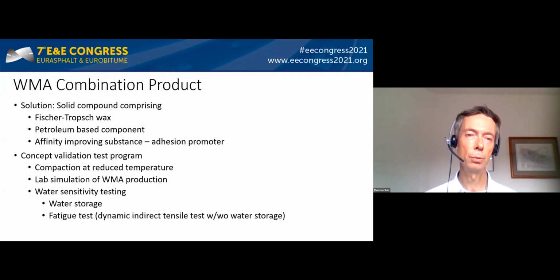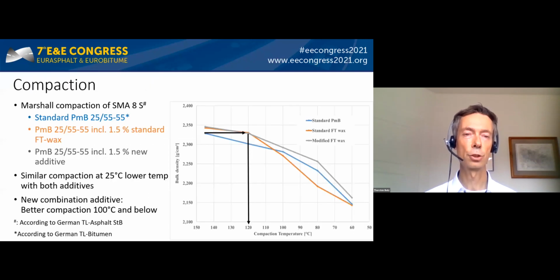Our concept was validated with the following test program: compaction at different reduced temperatures, laboratory simulation of warm mix asphalt production, and finally water sensitivity testing, applying dynamic indirect tensile test with and without water storage. For the compaction tests, we selected the Marshall method and used a stone mastic asphalt 8S according to German regulations. Three different mixes were produced. A hot mix reference using a standard polymer modified binder 25-55-55. The second was the same but included 1.5% of a standard Fischer-Tropsch additive, the well-known Sasobit. And the third, also the same mix but including 1.5% of the new combination additive.